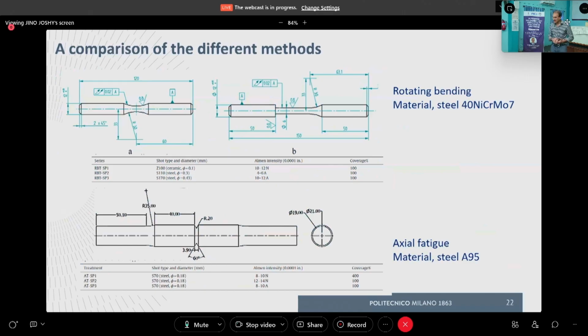In the second case, the material is a steel, A95 according to the API code, and the geometry is quite severe. We have a very severe V-notch, very, very severe. And here in the table, you see the different shot peening parameters we used for testing the different samples, let's say.